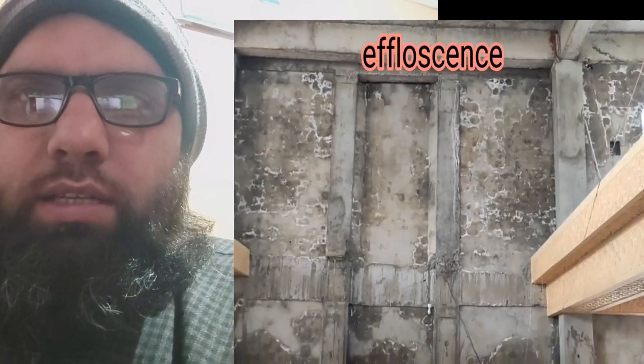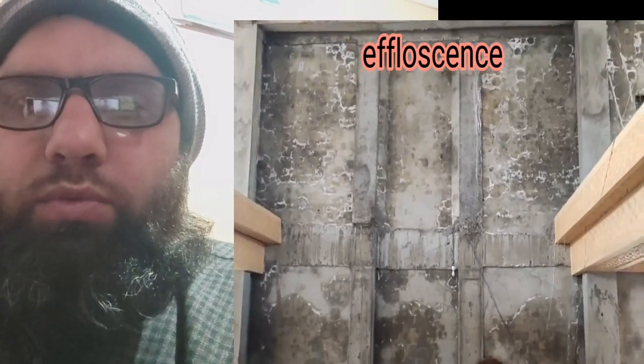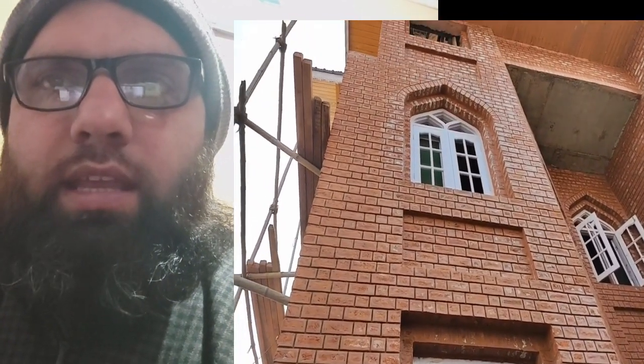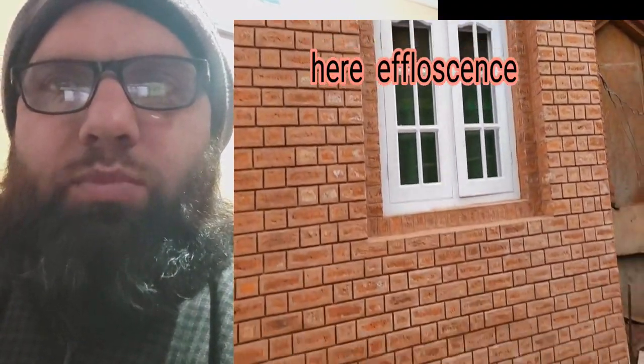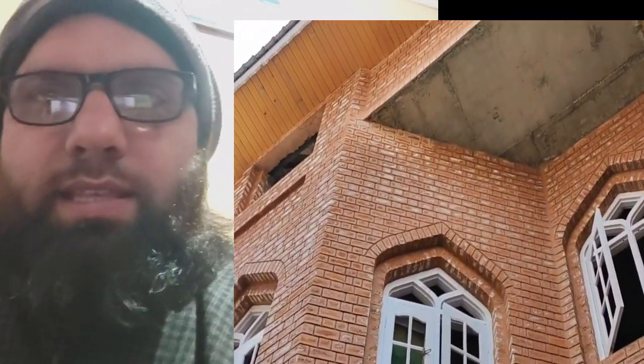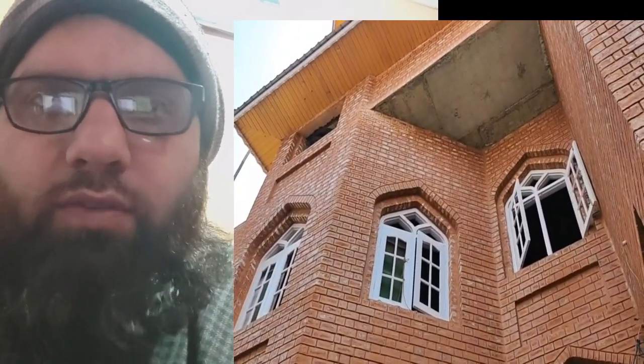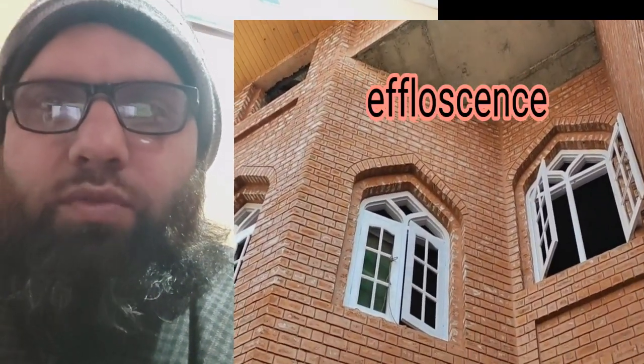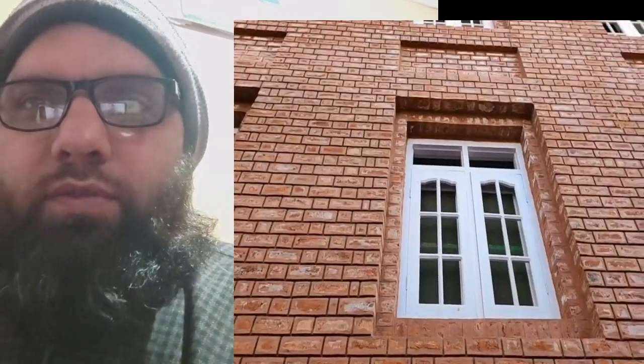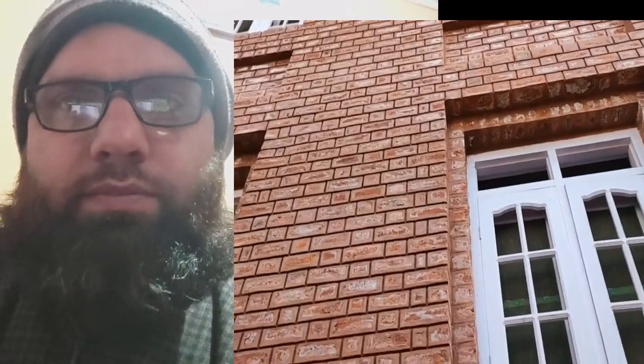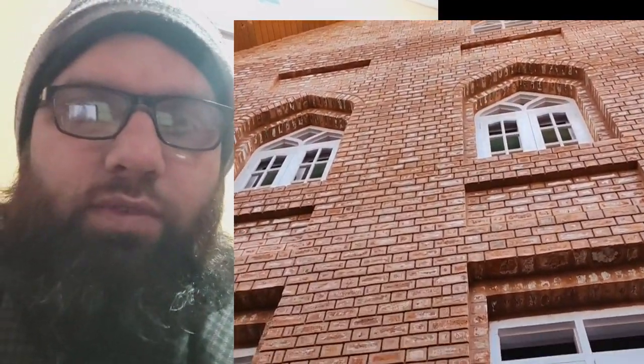How can you recognize it? How can you be sure that it is efflorescence? Actually, these are whitish spots with an abnormal and irregular appearance. They show up on surfaces which have suffered moisture. When the surface dries, the water evaporates and a few soluble salts observed in the water crystallize, and therefore the efflorescence appears.